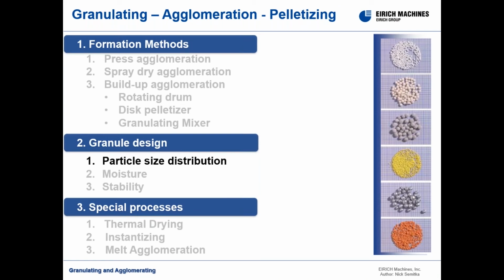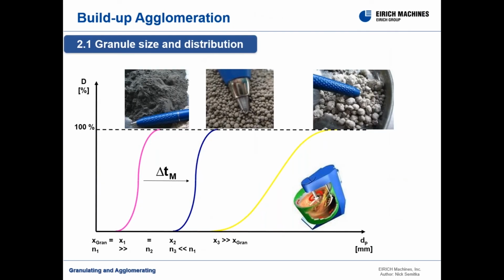It's difficult to control the granulation process if you cannot input the proper energy into the product while processing. In this slide, you can see that a certain distribution can be stable and the granules grow at the same rate, the pink and blue line. Lowering the energy input with a slower speed and extending the mixing time, the granules will grow and the particle distribution will get wider, as shown in the yellow line.